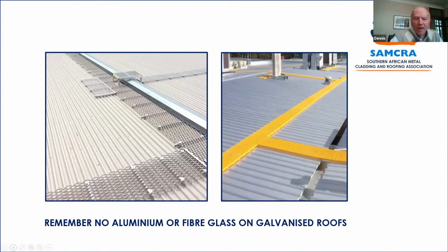And in my opinion, expanded mesh rolled from or manufactured from pre-galv is going to rust pretty quickly, and you'll probably find that you only have a life of 5 to 8 years in a corrosive environment before that mesh has rusted completely and is starting to attack your metallic coatings on your cladding. So if you're going to use expanded mesh, you're going to have to give it a pretty good paint system, and the old gungy black tar stuff that they used to put on is pretty effective there.